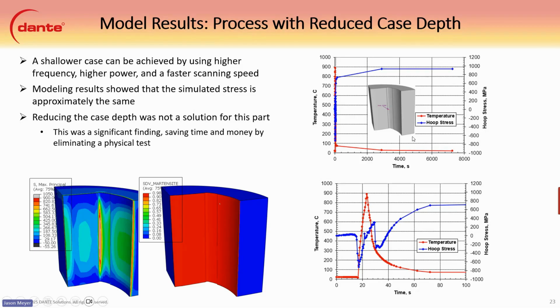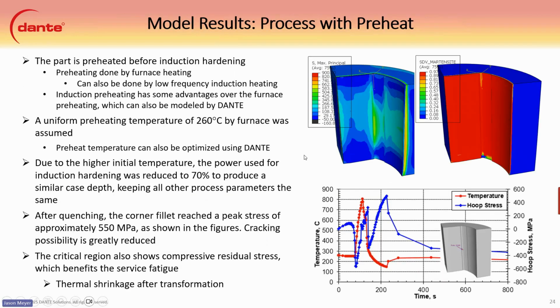You can see the time temperature results here, and you can see the hoop stresses here. It still has a pretty high magnitude. This section here that's very hard to see is actually exploded down to here. And again, it shows the same story that we saw with the baseline model. We start off really neutral, and then it goes into compression. And then once the martensite transformation occurs, we go back to tension here, and then it ends up a little lower magnitude, but still problematic as far as the quench cracking that's observed.